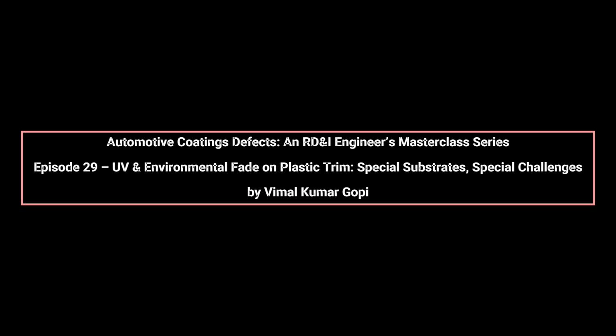Environmental contaminants further accelerate fade. Industrial fallout, road salts, and hydrocarbons chemically interact with the surface, oxidizing pigments and polymers. High humidity or acidic rain exacerbates surface oxidation. Water ingress at seams or along edges can hydrolyze polymer chains, weakening adhesion and allowing dirt to anchor more readily, which both reduces visual gloss and amplifies perceived fade.